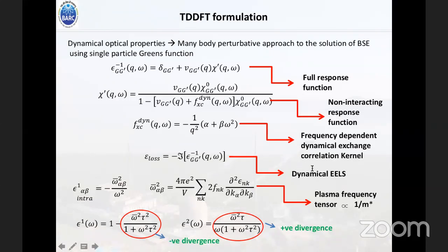This is the dynamical EELS, the electron energy loss spectra, which we have calculated, and it gives us some idea about the plasma frequency. We have also calculated the intraband effects. Since these are all metallic systems, one has to take care of intraband effects in addition to interband effects. If you look at this intraband effect, there is a plasma frequency sitting here, which is inversely proportional to the effective mass. If you calculate the real and imaginary parts of this epsilon, there is a negative divergence here and a positive divergence here. That should happen if it is a Drude system.